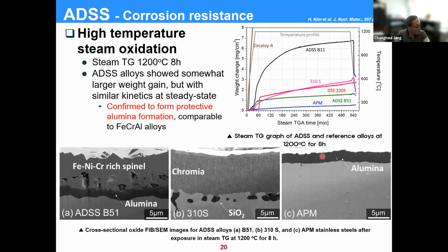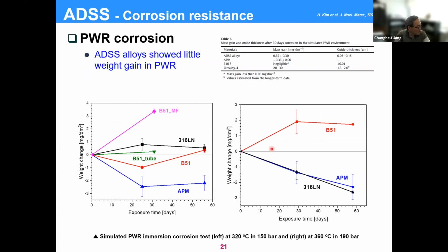So this one is a test result showing the improved corrosion resistance at high temperature. This one is the thermogravimetric test at 1200 degrees centigrade, and this shows excellent corrosion resistance compared to the conventional zirconium alloys by forming alumina and the Fe-Ni-Cr rich spinel structures. And also in the normal PWR environment, they have slightly positive weight gains. This one is actually more preferable than weight losses. If you have weight losses, you have some radiological problems in your primary coolant system. So a slight weight gain is the best property in the PWR environment.